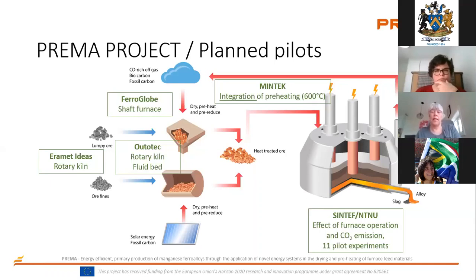It will be cooled down, but we need to know how the pretreatment will affect the furnace operation and how much we gain in CO2 emissions. So material from all these pilots, around half a ton or 1 ton, will be brought to SINTEF and NTNU, where we'll run pilot tests with the pilot submerged arc furnace, where we can feed around 0.5 to 1 ton of material. We will first run the experiments with material that is not pre-treated, and afterwards with the same type of ore material that is pre-treated. Then we will compare this, and based on that calculate the effect.